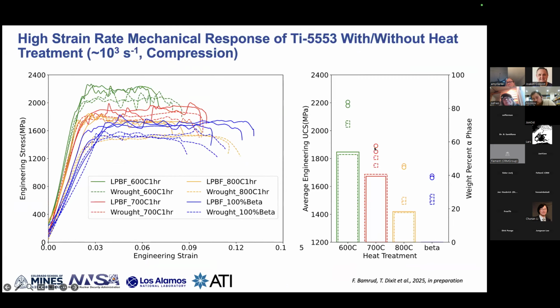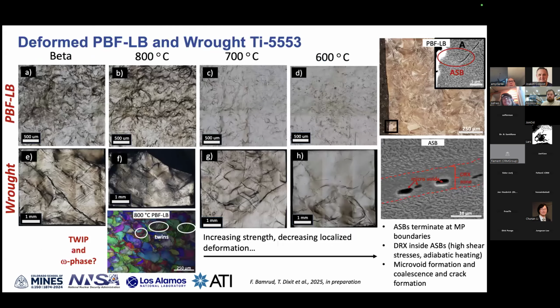So in summary, what we see here is as we increase the alpha phase amount, we obviously have higher strengths. But here we're comparing head to head the powder bed fusion to the wrought condition. And what's neat is we see that the powder bed fusion tends to outperform the wrought in all the conditions that we explored. If we look at the post-deformed samples of the powder bed fusion and the wrought, again, the beta condition as compared to the heat treatment condition, as we increase the amount of alpha phase, we tend to see decreasing localized deformation.